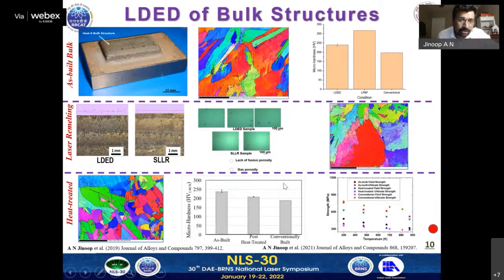Then we did the heat treatment to solve the other problem, that is non-homogeneity in the microstructure, and to achieve properties closer to the conventionally built samples. So we did heat treatment, and we could set 1177 degrees Celsius, which is the preferred heat treatment temperature for the material as per the standards. So we went to the heat treatment, and we could see coarsening of the grains, and we could see that the orientation is random, and the mechanical properties are found to be closer to the conventionally built Hastelloy sample in terms of microhardness as well as the yield strength and ultimate strength.